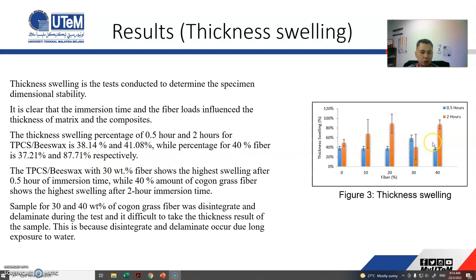That is for 2 hours. As you can see here, the trend is slightly different from the water absorption, where the sample with fiber showed higher swelling as compared to the matrix. The samples with 30% and 40% fiber disintegrated and were delaminated during the test. So it's also difficult to take the testing results of these samples because when they disintegrate, the thickness cannot be measured accurately. But anyhow, this shows that this material is environmentally friendly for sure.